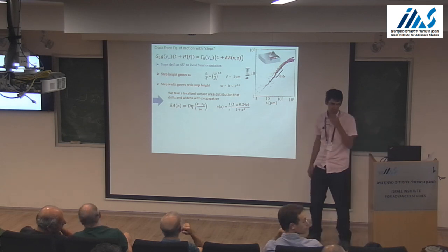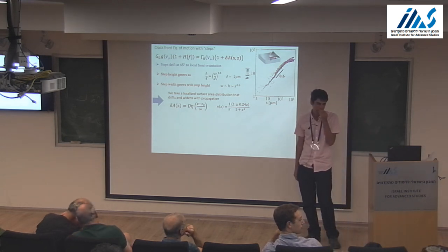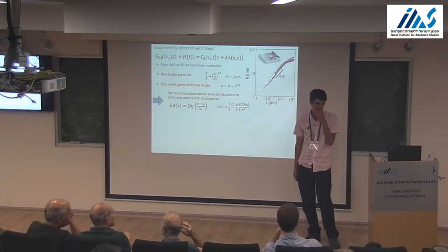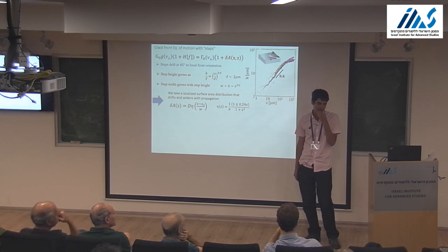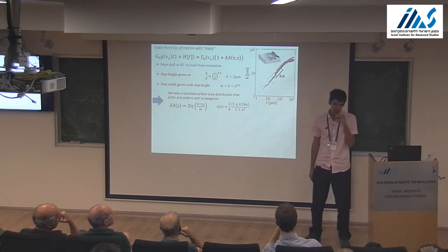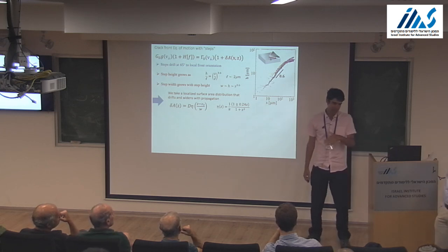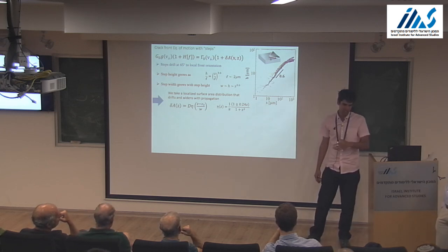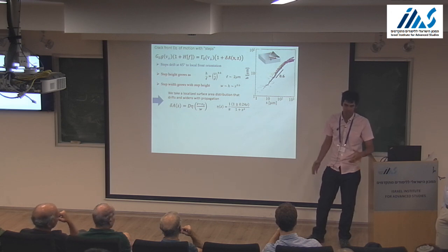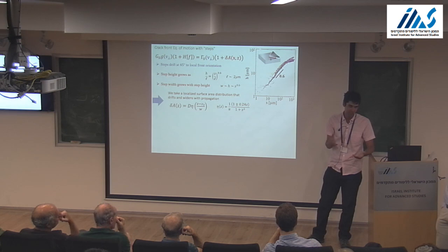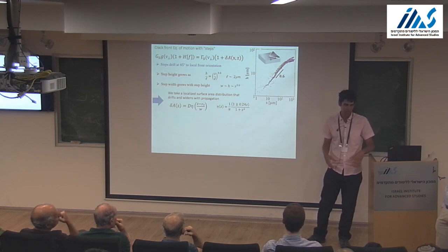Thanks. So with the transitional region where you have the mixed steps and microbranches, how sharp do you think the transition is? Well, for the specific system I investigated, we see a transition between 0.05 and 0.1 of the Rayleigh wave speed, but I really don't know much more.